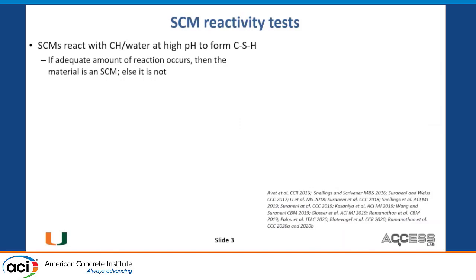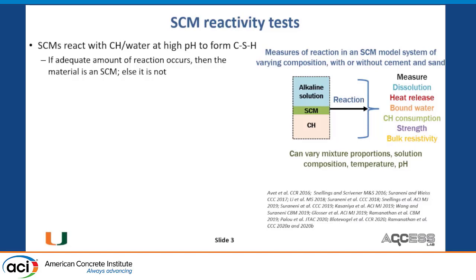Let's take a look at how the SCM is actually reacting. A very simple model system: we have an SCM, calcium hydroxide, and some kind of alkaline solution. The SCM will react with the calcium hydroxide and/or the alkaline solution. It will react even at room temperature, but really you need to test it at 40 or 50°C to get measurable levels of reaction. What can you measure? You can measure dissolution, heat release, bound water, CH consumption, strength, bulk resistivity. You can vary these proportions as much as you want.